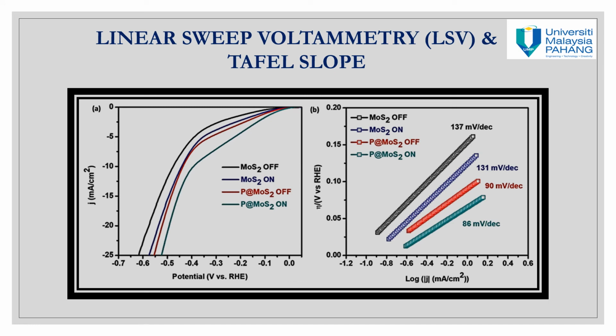In a similar approach, the Tafel slope was plotted, and the Tafel slope is usually used to interpret the mechanism involved in the hydrogen evolution reaction. The pure MoS2 is high in both dark and light illumination conditions, that is 137 and 131 respectively. During the light on condition, the catalyst usually generates more charges and contributes to HER activity. When you see the phosphorus doped MoS2, the Tafel slopes are much smaller, that is 90 and 86 in the dark and light on conditions respectively. Thus, we can say that the smaller the Tafel slope, the faster the charge transfer rate in the electrode. That means the P doped MoS2 is much better.